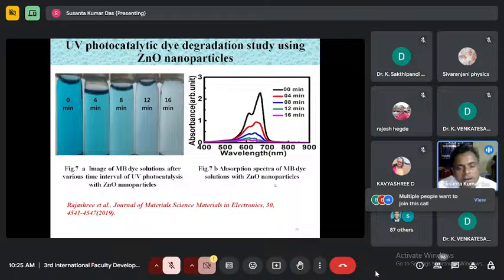And you can see, exactly after half an hour, we started the light. At that point, we call it a 0 minute light exposure, and the dye solution was very deep, and you can see the absorption peak was also very high, the 0 minute black color peak. You can see this is a typical absorption peak of methylene blue. So that was very high. Then when we increased the exposure time, every interval of exposure time, we need to switch off the light, collect the solution, go for separation of nanoparticle, then go for this absorption study. This way we continued, and this is the general procedure.